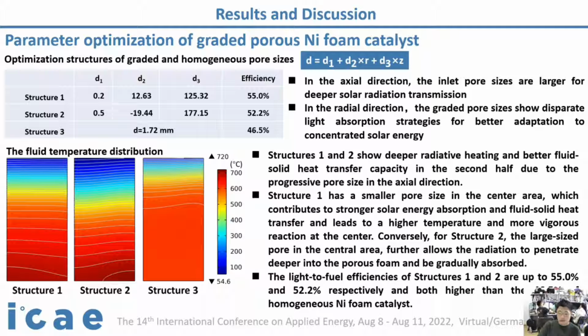The light to fuel efficiency of structures 1 and 2 are up to 55% and 52.2% respectively, and both higher than the 46.5% of homogeneous nickel foam catalyst.